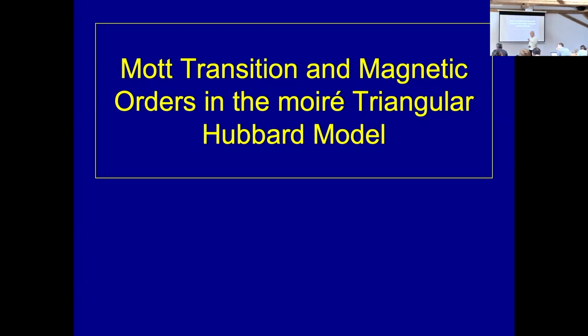Good. By the way, let me just add something. What controls TC is the entropy of the insulator. Basically TC is some ratio of energy difference to entropy difference. So if you make this entropy difference much bigger, then you can raise TC. And this is what happens in SU(N) models. If you extend the degeneracy, you will push TC.